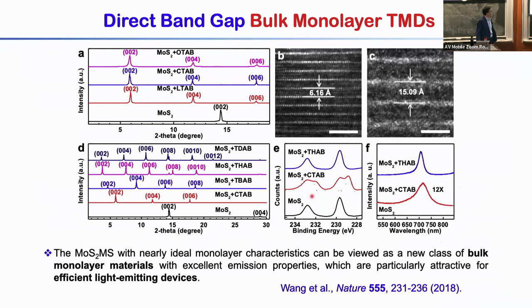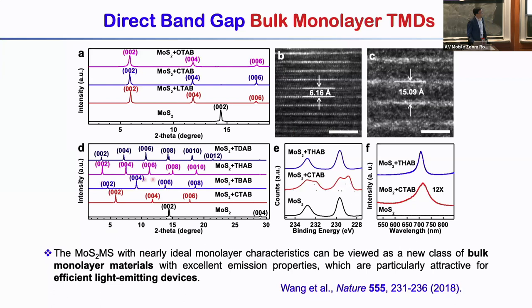This approach is actually very flexible and can be extended to any kind of 2D materials. We can use different molecules — for example, with smaller or bigger molecules to control the interlayer expansion or interlayer coupling with different periodic distances. The XRD pattern shows that the intercalation materials show a pure phase, and you can see the diffraction peaks are also very sharp, really showing the heterostructure is truly a high-quality structure. In the case of TMDs, for example MoS2, multiple layers have an indirect band gap. After intercalation, we actually decouple the interlayer interaction and can turn them into a direct gap material with very strong PL emission — actually stronger than a single monolayer because we have much more material and a much larger optical cross-section, which could potentially be interesting for practical devices.